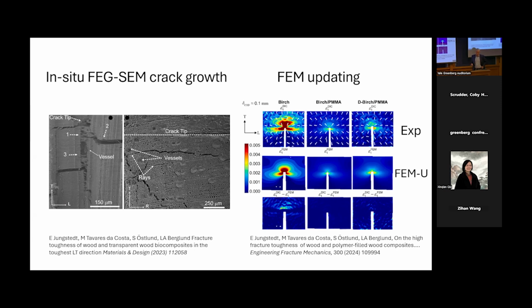We then used numerical analysis of this mechanics problem. On the top, you have experimental data, so we're locally measuring the strains. This is for unmodified birch, birch with the polymer, and delignified birch with the polymer. So these are the experimental results. We look at the damage mechanisms at the crack tip, and then we model this with finite elements. The procedure we're using is that we have start values, and then we use the local strain fields, and we know the global stress. So then we can update the material properties, which is a reasonably complex problem because it's an orthotropic material with several elastic constants. And the difference between the predictions and modeling is reasonably good, except for maybe the birch case.